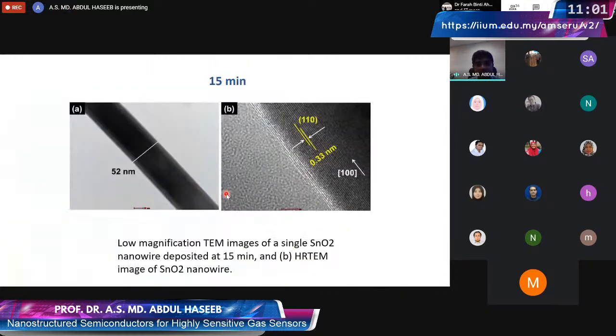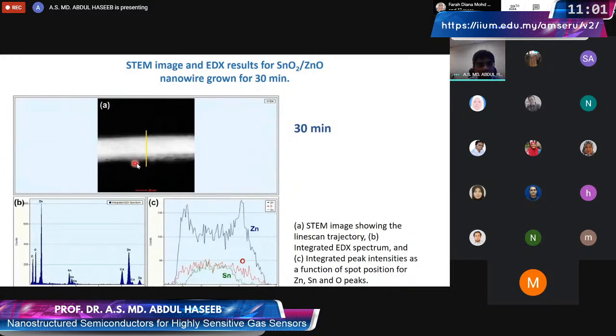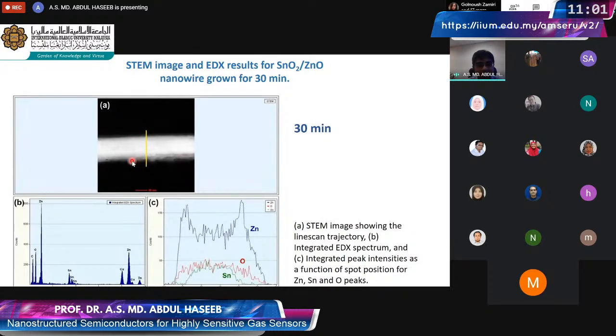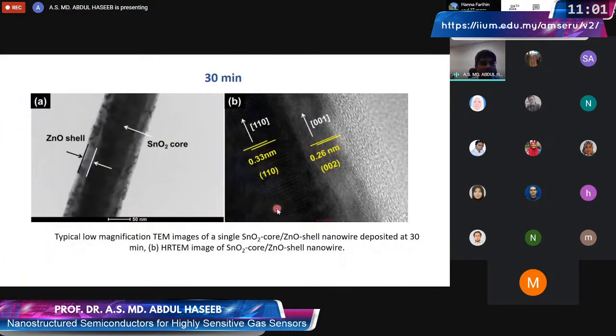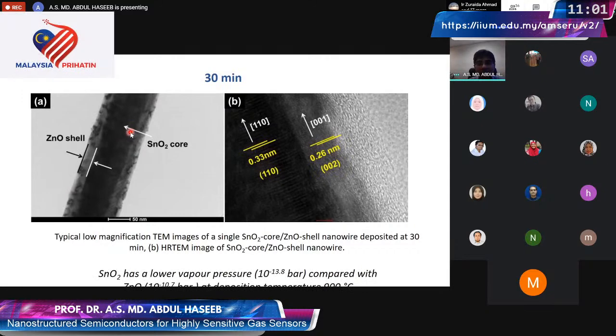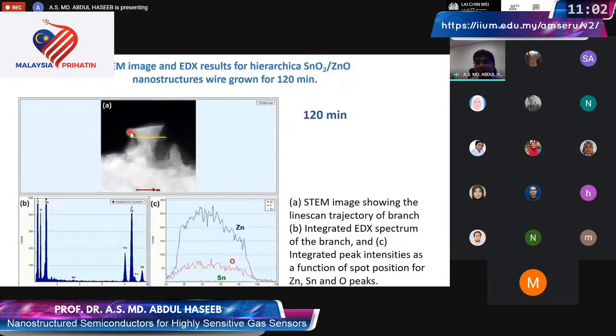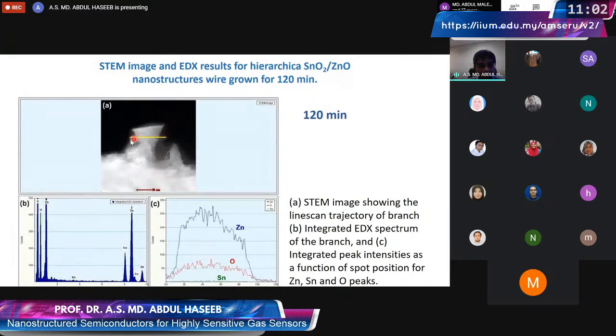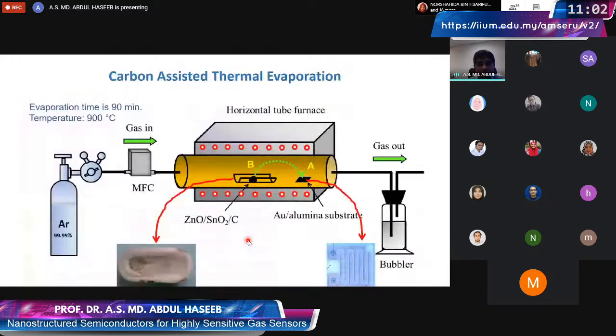And then with time, at 30 minutes, when it becomes rough at the surface, we see that additional material is depositing, and the rough things are zinc oxide, as you can see from the higher signal of zinc on the surface. We get a core-shell structure at 30 minutes, zinc oxide and tin oxide. Then when we keep running the experiment to 120 minutes, we see that the branches are forming. You probably remember the side branches, and when we look at one of them, we see that the side branches are basically zinc oxide. So the stem, which is tin oxide, is surrounded by a layer of zinc oxide, and then the branches come out. Quite interesting.